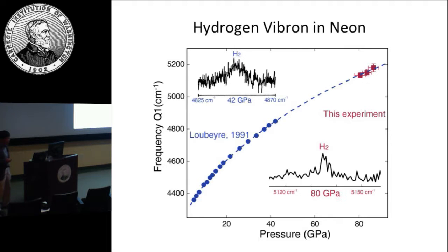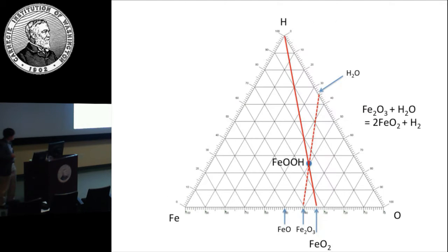Okay, now we also have to prove there's hydrogen there. The hydrogen at this temperature, 1800 degrees, is very mobile. So it diffuses out into the neon, and it shows as a hydrogen vibron peak in neon, at 5130-something. This hydrogen in neon had been studied previously by Loubeyre, 1991, and they only studied it to 40 GPa, and ours is at 80 GPa, so it falls right on their extrapolation. So there's no doubt this is hydrogen, and later when we reduce the pressure, it just tracks back. So now we demonstrate this reaction is real: at high pressure, the water plus the hematite will become FeO2 plus hydrogen.